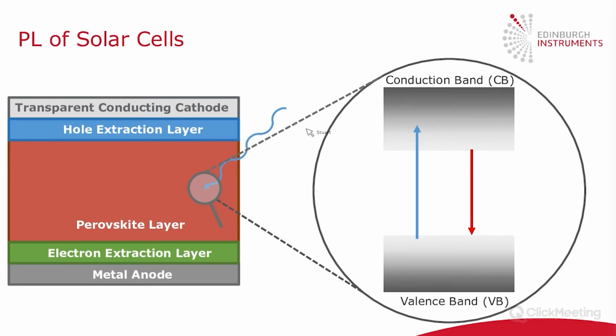Photoluminescence is a powerful way to investigate these materials because when you excite the perovskite, you promote electrons from the valence band to the conduction band. This is the same process that occurs when these solar cells are illuminated under the sun to generate electricity. And so the behavior of these when they're excited is important to their solar cell performance. You can either look at the intensity of this decay back to the ground state, generally higher PL intensity means higher solar cell performance, and you can also look at the lifetime.